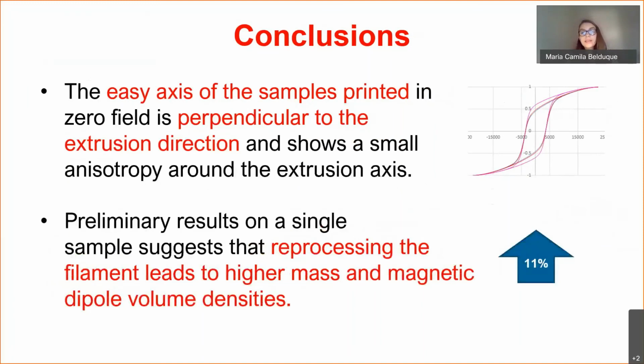Similarly, the easy axis of the samples printed in zero field is perpendicular to the extrusion direction and shows a small anisotropy around the extrusion axis. The easy axis of the samples printed in a magnetic field is parallel to the field direction. Additionally, preliminary results on a single sample suggest that reprocessing the filament leads to a larger mass and higher magnetic dipole volume density.